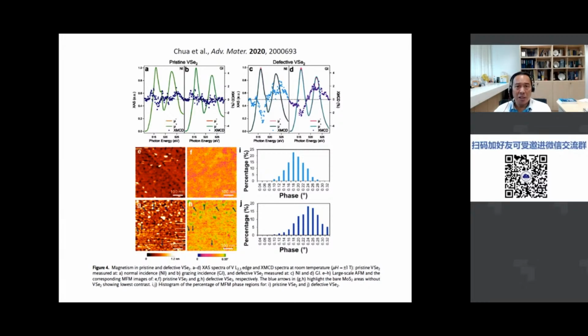So these are the magnetic measurements. First, the XMCD measurements above. You can see that for the pristine vanadium diselenide, the XMCD signal, the noisy line, is approximately 0. But when she annealed the sample in vacuum, and there are more defects on the surface, you can see a slight dichroic signal appearing here, indicating that there seems to be a direct correlation between these line defects and magnetism in the surface.